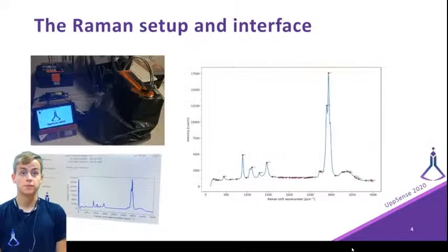Raman spectroscopy is a well-established spectroscopic method which measures vibrational properties of molecules. Historically, it has been limited by a lack of sensitivity, but advances in instrumentation and methodology have increased its applicability. One such methodology, SERS, surface-enhanced Raman spectroscopy, is a distance-dependent phenomenon which increases Raman spectroscopy signal intensity at colloidal metal surfaces. Utilizing a green laser and an optical detector, we can perform Raman spectroscopic measurements which selectively boost the BPA signal without increasing background signals.